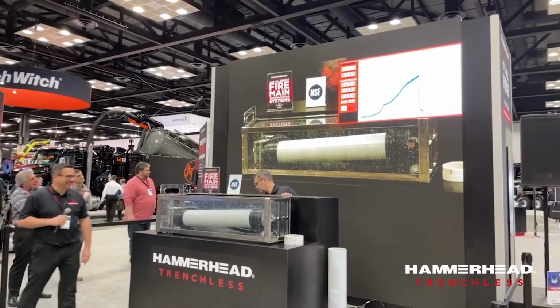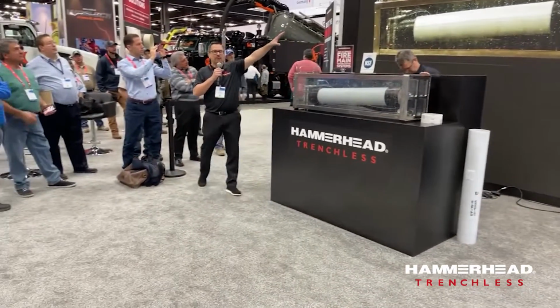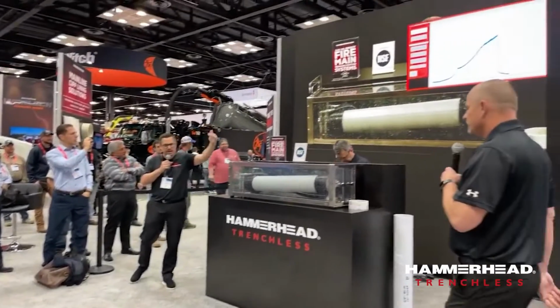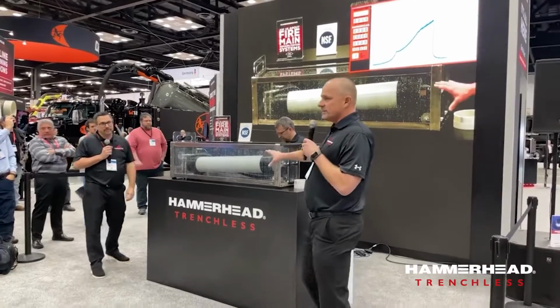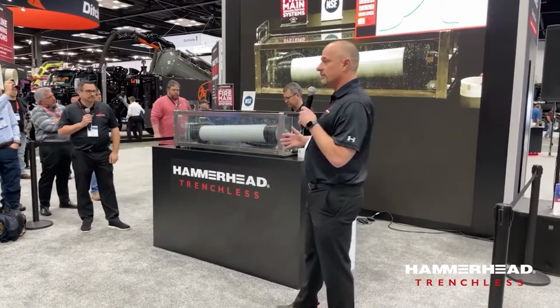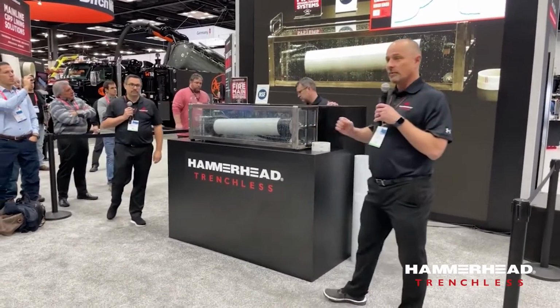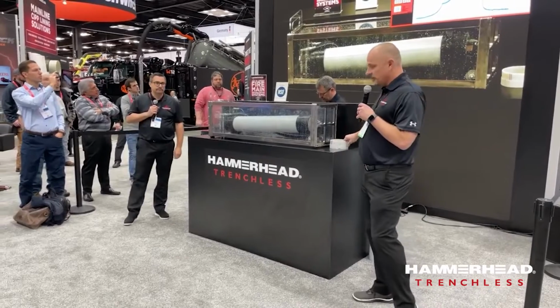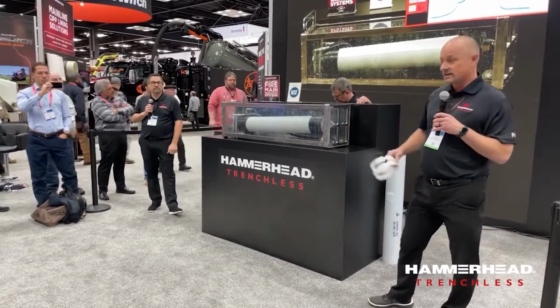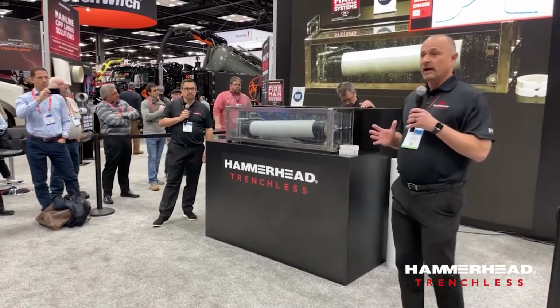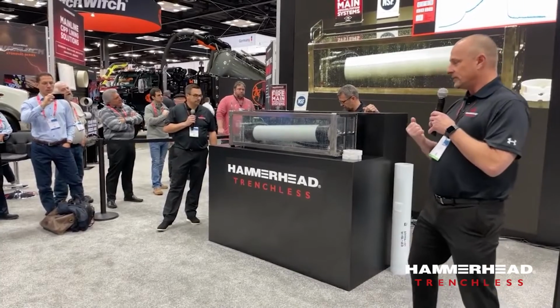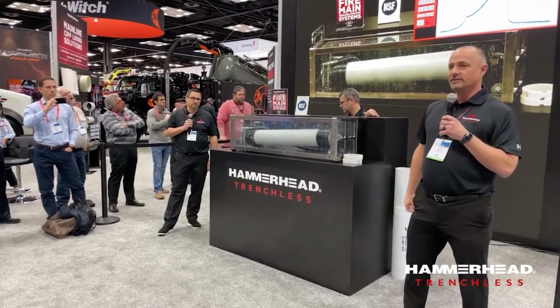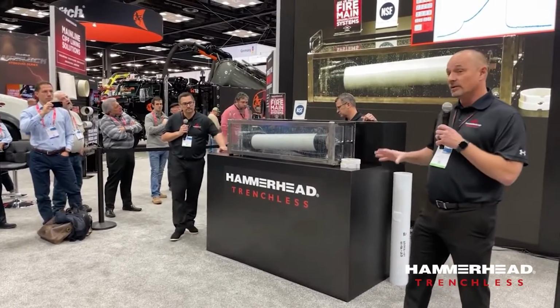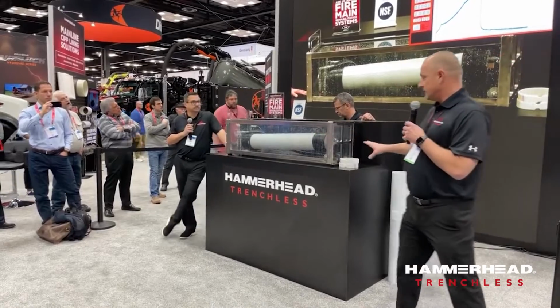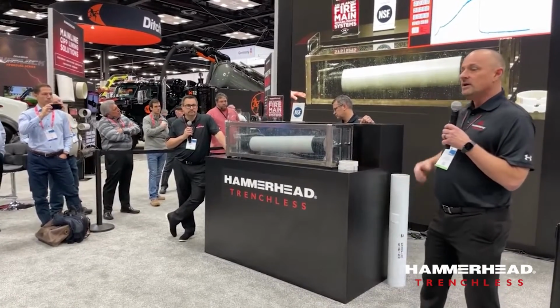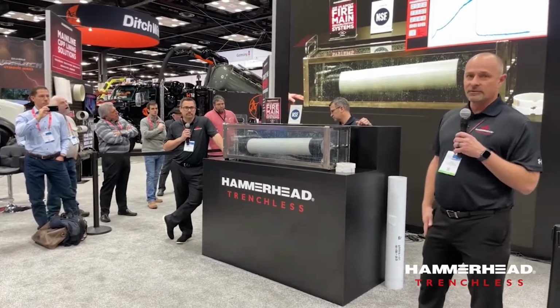Wow. So there you go. So at this point, you would have this information, Dave, and we can validate the quality of our liners if they meet the design standard or things of that nature, correct? That's correct. And as a basis of design, you use this to determine what your estimated pressure ratings are for your material. And then in the field, if you want to confirm that, you can capture full samples and do what we call a split ring test, and it's an ASTM D2290 test. You're basically taking the full hoop and you're pulling tension on basically a cylindrical piece that's split in the middle, pulling tension to failure. That gives you a very comparable, actually almost identical performance. If you look at the geometry of this versus the geometry of the sample you test in a lab, you're going to have virtually identical performance. And that confirms your design and performance of the material.